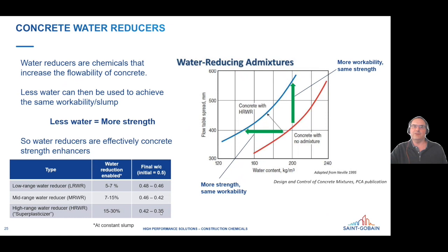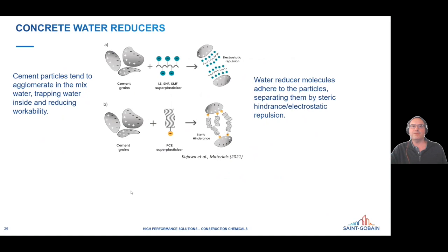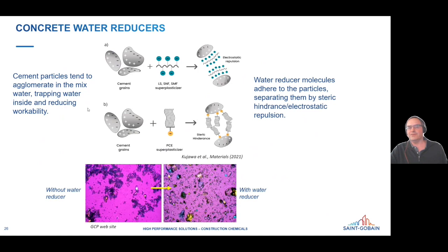So how do these concrete water reducers work? Well, again, it's really a very similar process as the grinding aid. It's a dispersant. So it's just happening in water instead of in air, but the cement grains in water tend to agglomerate as well. This traps water between them, which doesn't then contribute to the flow. And so that's why you have a stiffer paste. The chemical goes in there and pushes the cement particles apart and effectively releases this water inside, and you get the increase in workability. So again, there's a little optical micrograph on the left without the water reducer. You see the agglomeration of the particles, and with the water reducer, all the particles are now separated, and you're going to have much better flow.